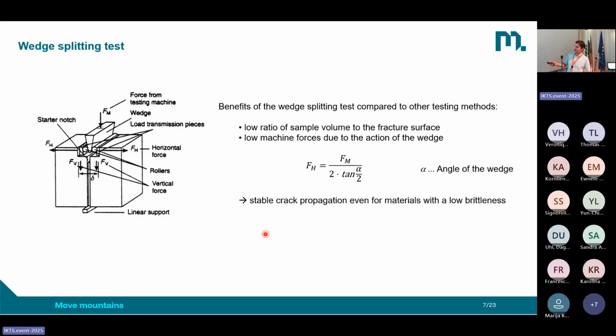We have a cubic sample, and here you see a wedge, which is then pushed downwards by the testing machine, and you see here rolls in contact with load transmission pieces, which transport the vertical load applied here into a horizontal force acting on the sample. And this horizontal force is then splitting the sample. The crack will initiate here and propagate along the starter notch through the sample.